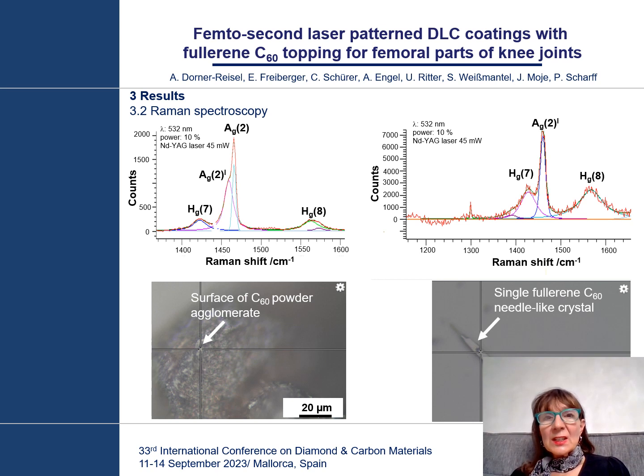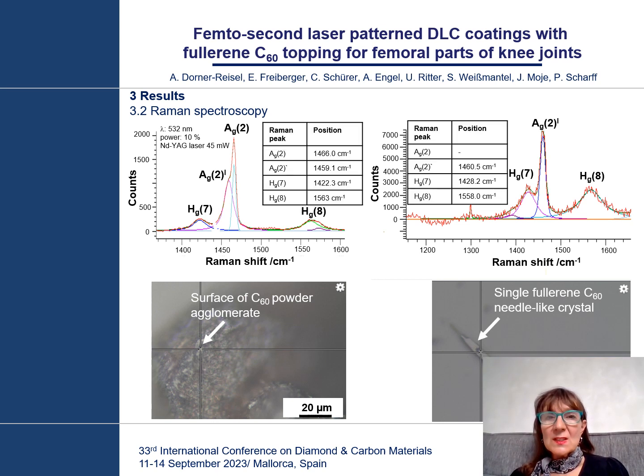Looking at the needle-like C60 crystals by Raman spectroscopy, we find out that C60 forms chains. This is evident by this Ag2 peak at 1460. The starting powder, on the other hand, has a much higher content of monomers.